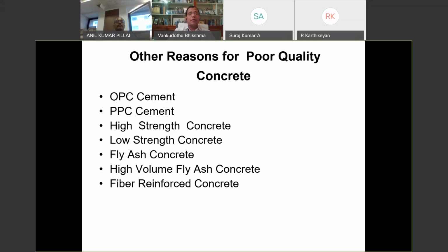With PPC also, sometimes cracks will come, because the percentage of ordinary Portland cement and PPC, that is 75% and 25%, we normally say is the optimum dosage. Suppose if your PPC percentage is too much, then there is a possibility of getting cracks again. So we should think about the optimum dosage and then use it for our concrete after making several trials. In high strength concrete also, due to excess cement, cracks will come. In low grade concrete, due to low percentage of cement, bulging takes place due to improper setting.